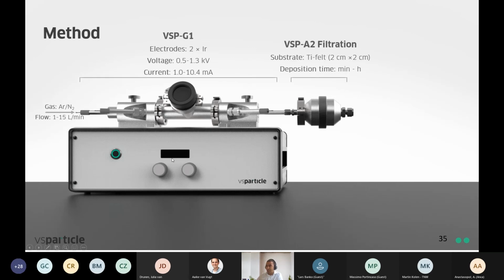They used the VSP-G1 Nanoparticle Generator and a VSP-A2 Filtration accessory. The Nanoparticle Generator was equipped with iridium electrodes. They could vary the voltage between 0.5 and 1.3 kilovolts, and the current between 1.0 and 10.4 milliamps. They used an inert gas, so either argon or nitrogen, and they could vary the flow between 1 and 15